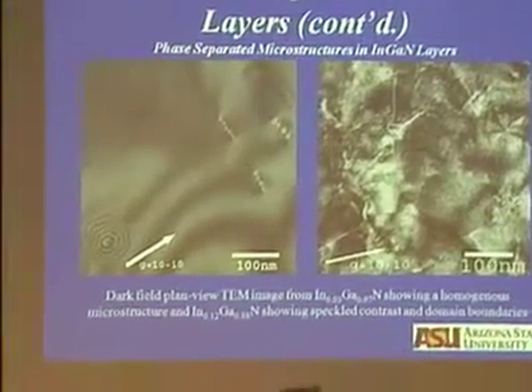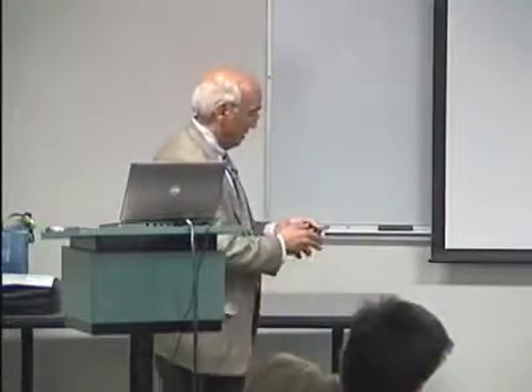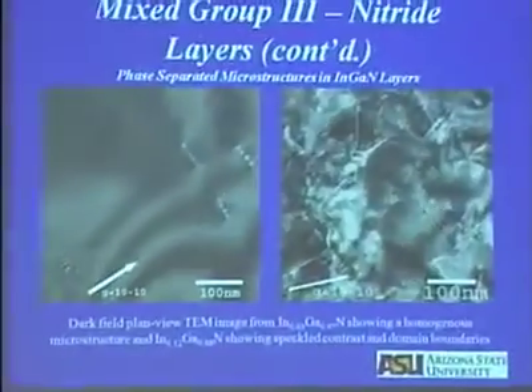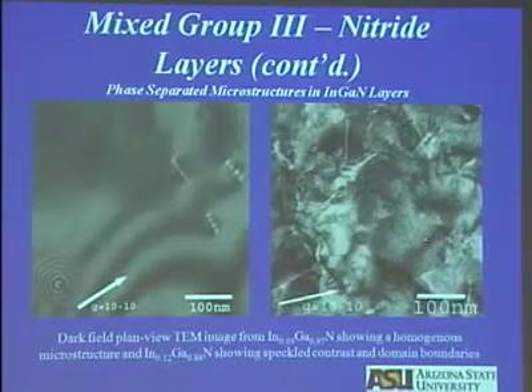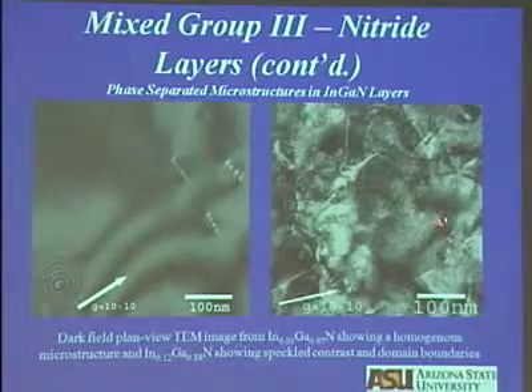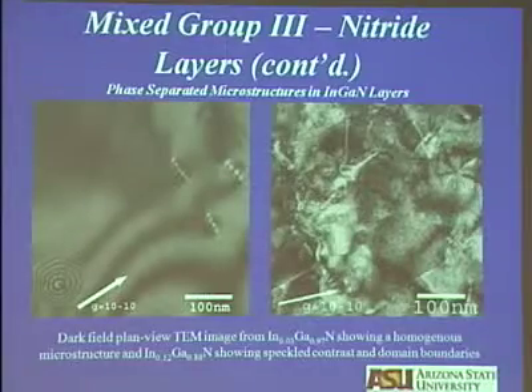So when you grow on 001, what we showed is the phase separation occurs along the 1-100 or 11-20 direction. There are three directions of each in the basal plane. If phase separation occurs along one direction and neighboring regions phase separate along another vector, you will produce the boundaries. We don't fully understand the structure of these boundaries, but we can rationalize. This is speckle structure, which I said is due to phase separation. And what is the correlation between this one and this phase separation? I'll try to illustrate in the next slide.